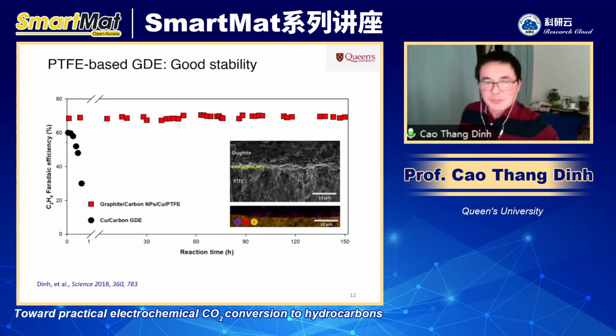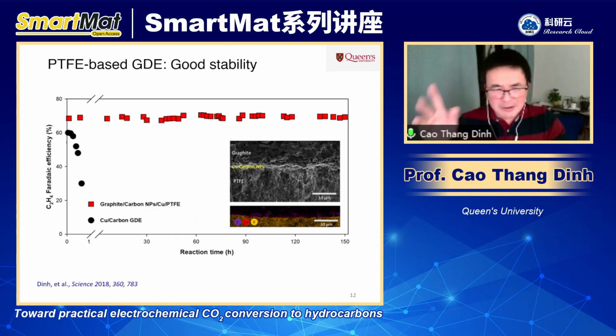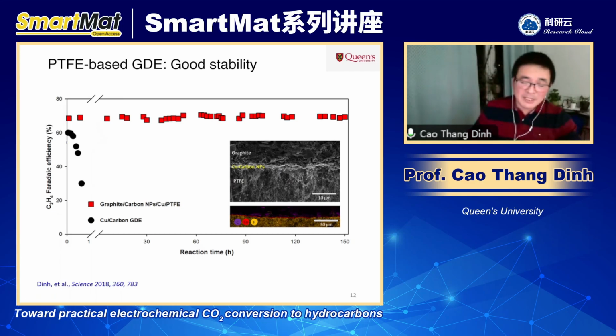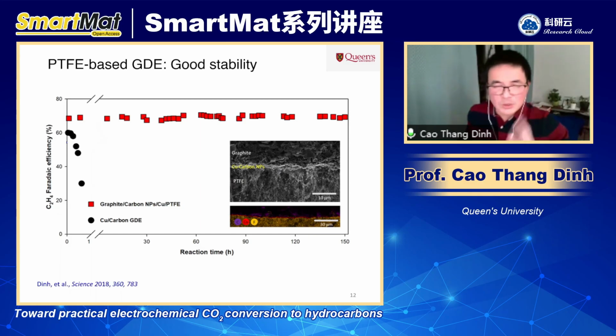And it's working just perfectly. Now you have the PTFE layer, which is pretty stable. And then we run the reaction at, I think, a current of around 100 milliamp or so. And then we can see that the ethylene, when we use the PTFE substrate, can be maintained at around 60-70% for over 100 hours. By that time, I think it's one of the longest for CO2 conversion to ethylene.